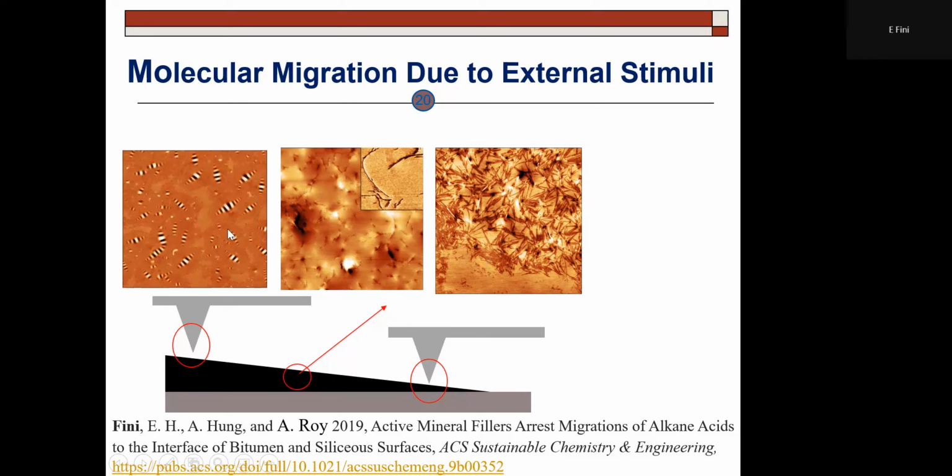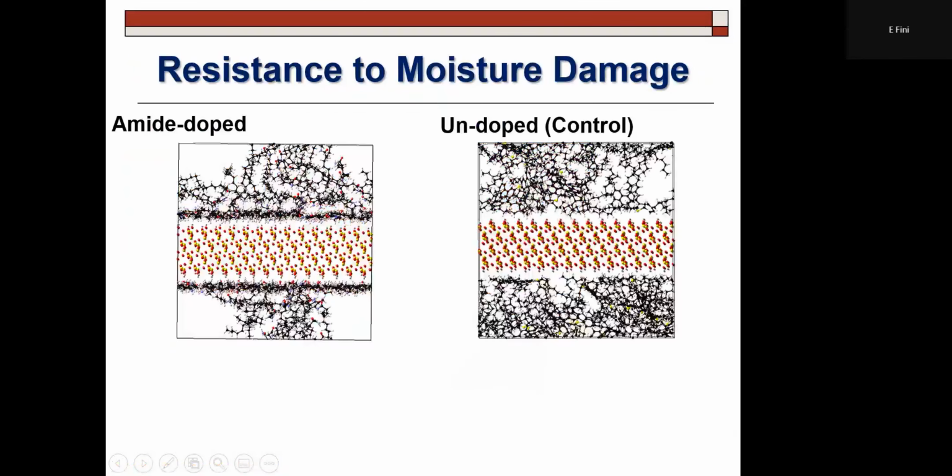So that was important because when the water comes in, the water wants to get between the black and the gray, literally wanting to replace the bitumen. So it will get to the interface closer to the bitumen and glass surface, and what it sees is actually this structure on the right. If water sees this and starts cutting the bitumen away from the substrate, then right there you have moisture damage. So now that we understand what type of structure, what type of molecule we have at the interface, maybe we can control it and prepare some built-in reinforcement mechanism to avoid the damage.